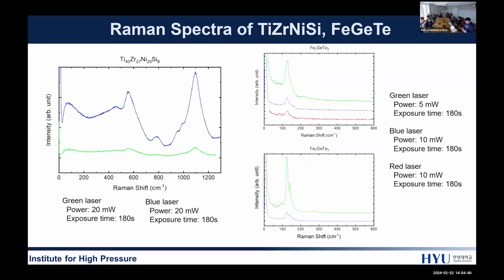In addition to albite, I tried to measure the metallic glass titanium, zirconium, nickel, silicon, and the 2-dimensional van der Waals material iron, germanium, tellurium samples. Unfortunately, the first result showed poor sample conditions, so I could not measure more. I got new samples recently, but because of the time limit, I could only do some early tests, and this is the test of my bulk samples measurement.